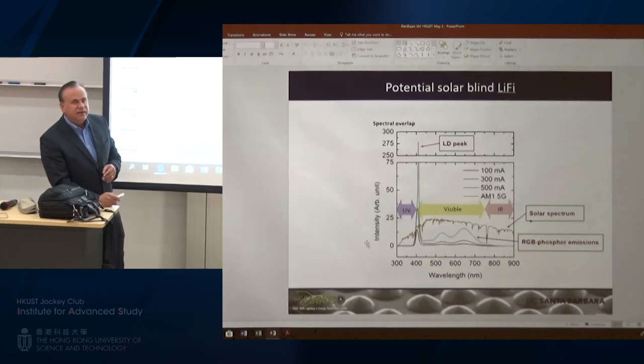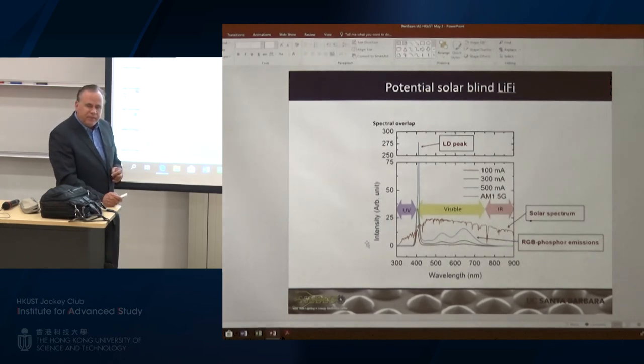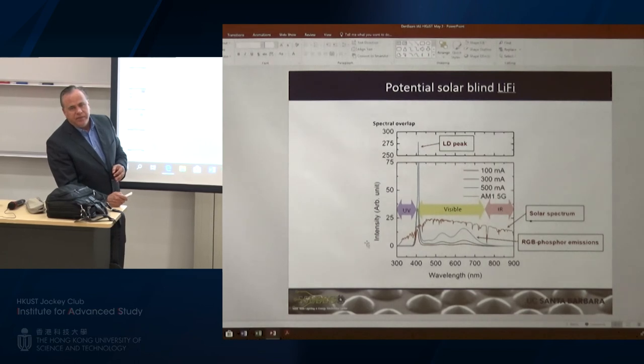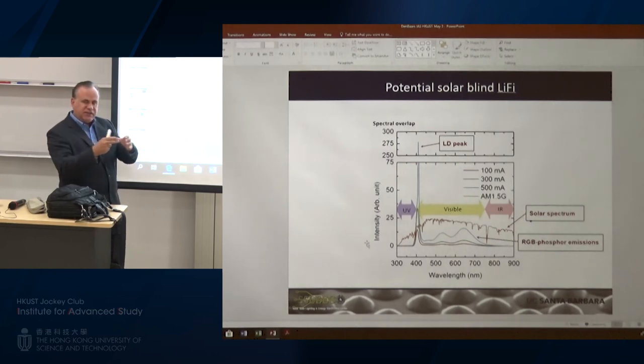Photodetector power. So the third question is about the micro LED. If you go to smaller and smaller sizes, is part of the reason the efficiency is lower the extraction, because you have more and more side emission? It's two reasons. Initially we thought the dominant reason was extraction, or the contact area blocking it, but it's not, it's more fundamental. It's the surface recombination. The effect of the surface gets more intense, and at a surface you've broken the crystal, so you get deep level states, and the electron and hole recombine at the surface non-radiatively, rather than in the quantum well. We call it surface recombination. Other people just call it defect recombination.